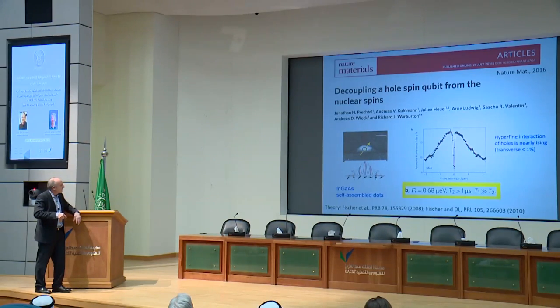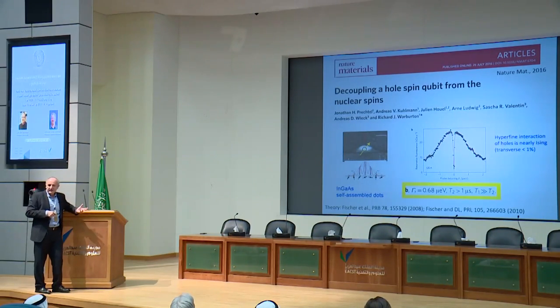the T2 time of a hole spin in an indium gallium arsenide self-assembled quantum dot can reach T2 times longer than a microsecond. So this is full of nuclear spins, but the fact that we are dealing here with a hole prolongs the time by a factor of 1,000.